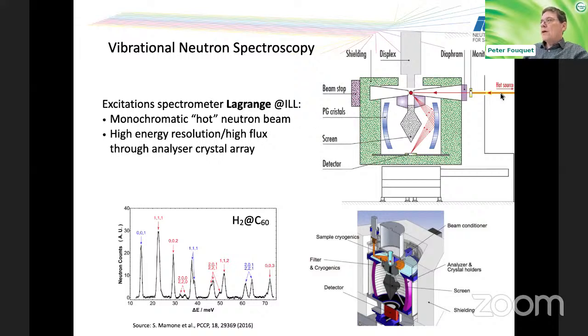You come in with a beam from a monochromator that comes directly from our hot source, illuminate the sample, and then you have a large shield, you can see it better in the 3D view around here, that large shield of monochromator crystals. So they select an energy, but they are built all around here. And then you illuminate with this detector at the bottom of the instrument. And this gives you a very large signal. And then scanning through energies, you can record a spectrum. And here's an example of hydrogen in C60 buckyballs. And you see the very sharp lines that you can detect.